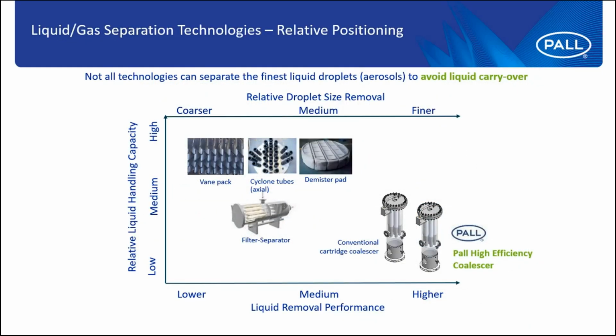Again, a comparative study for liquid removal from gases. We see that not all technologies can handle very fine liquid droplets and so avoid carryover. In certain applications, it's fine to remove a bulk of the liquids. There we use some vane pack, cyclonic or demister pad. It helps to reduce the liquids to certain levels. But here, for sour gas amine absorber protection, we definitely need high efficiency, because the fine droplets that generate issues of foaming inside the loop need to be removed very efficiently.